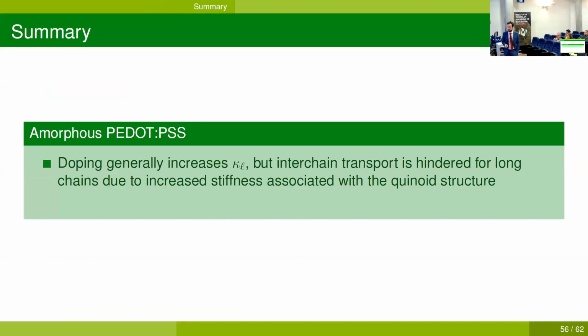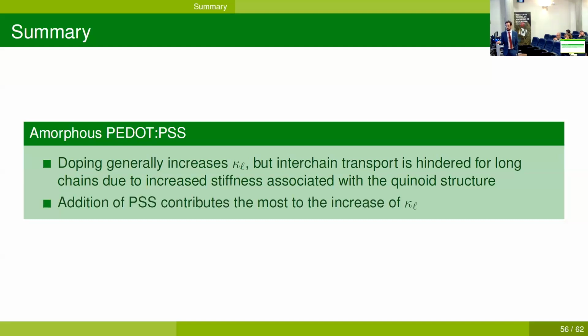So to give a summary, we have investigated amorphous PEDOT:PSS, and we have assessed the impact of doping on the lattice kappa, where doping generally increases kappa L, but interchain transport is hindered for long chains due to increased stiffness associated with the quinoid structure. We have also found that adding PSS itself to the mixture is the factor that contributes the most to the increase of kappa L.